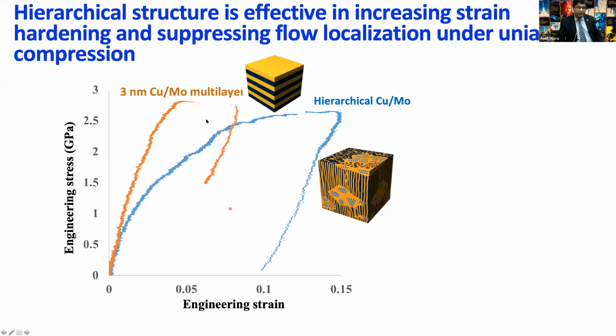So very interesting structures. The question is, what are the properties? First looking at the compression, that's the 3 nanometer multilayer structure that I showed before. The hierarchical structure has a very pronounced elastic-plastic type of transition because the two composites deform in different ways. The copper islands that have those nano dots of moly have a characteristic stress-strain response.